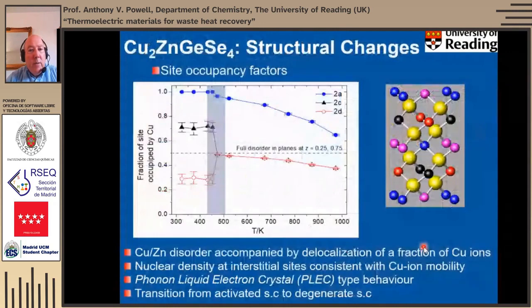Now, fortunately, the PhD student who was doing this, whilst initially disappointed, decided to look at this in a bit more detail. And what he found is actually, if we look at the site occupancy factors, initially we have this disorder between the copper and the zinc sites. So it's not a 50-50. It's a slight preference for the copper in one site, the 2C site, than the other site, the 2D site. And then there's a copper that fully occupies this 2A site. So this is our room temperature structure.